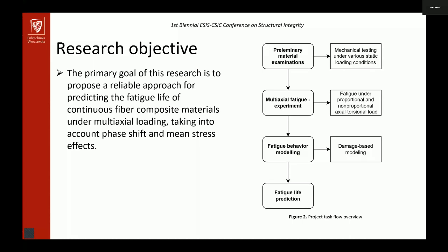The first step is material characterization under monotonic load, then multi-axial fatigue experiments, fatigue behavior modeling, and then fatigue life prediction. The fatigue behavior modeling was based on my own experimental research on CFRP, and then I took data from the literature to see how it works for similar material from the same group, but with different stiffness.